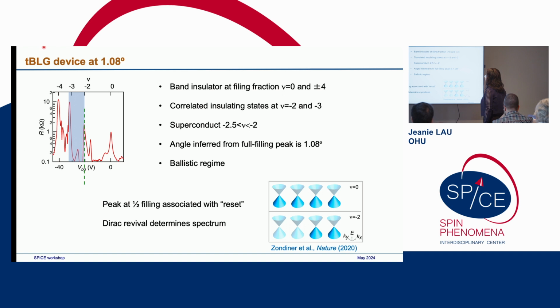Another thing I want to draw your attention to is these peaks at filling factor 2 and 3. These are associated with the so-called reset of the Dirac spectrum, or the Dirac revival story. This is work done by a number of other groups, which means you have these 4 mini Dirac cones from the spin and valley flavor, and every time you fill one, you fill the lower half of one and then reset to fill the other. Basically you go through this reset of filling of the mini Dirac cones, and this has also been verified by the Rxy, the density measurements. When we fill 2 holes per unit cell, the effective charge density resets to 0.